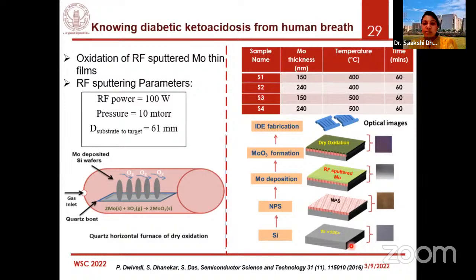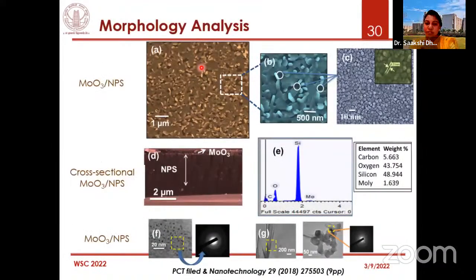So we tried developing some sensors with molybdenum trioxide, the metal oxide, on nanostructured silicon, and we tried exposing them to different VOCs. After the process we followed to fabricate this molybdenum trioxide on the whole wafer, we could see a nanoribbon kind of structure. We also played around with the thickness of molybdenum trioxide, at what point it shows P-type and at what point it shows N-type behavior. All of that was done. With the help of test structures, we could do Hall effect measurements and see what type of material is being formed.